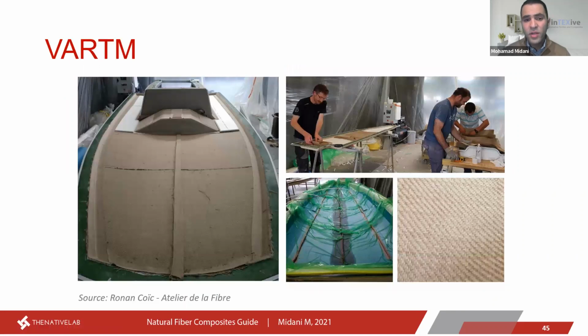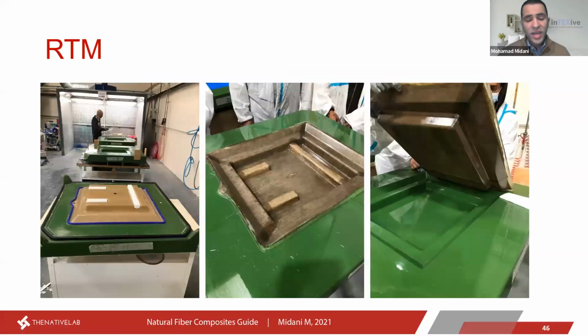Another technique that is suitable especially for larger structures that are perhaps produced in smaller quantities is vacuum assisted resin transfer molding. So it's mainly suited for applications like marine and other applications that require a smaller number of parts to be produced. Also resin transfer molding is another important technique, especially if I need to have a part with a two-sided surface finish. I have to have good surface finish on both sides. So resin transfer molding would definitely be the process of choice. It provides high fiber volume fraction, up to 60%, because of the high consolidation pressure. And it's suited for large production quantities, but still for small parts.